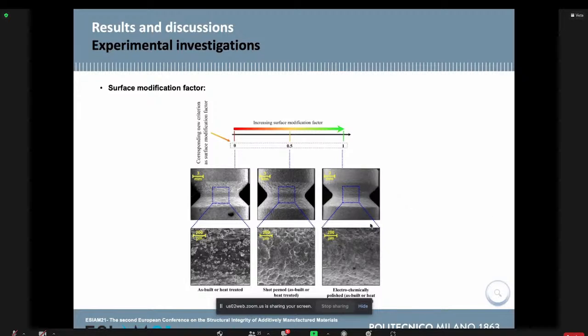You can see here in the as-built or heated material, we have lots of surface notch roots. By applying shot peening, it's going to be better. But after applying electrochemical polishing, it becomes better and better, and we have the best surface quality in the electrochemically polished condition. Then we assign different numerical values to each of these three conditions.